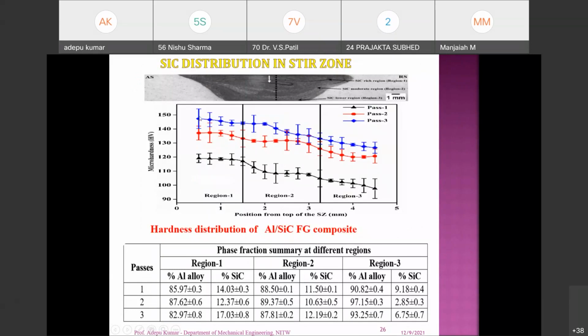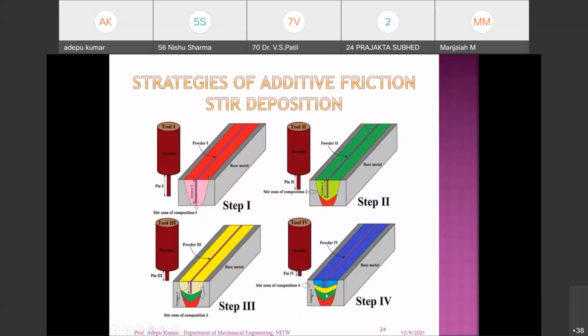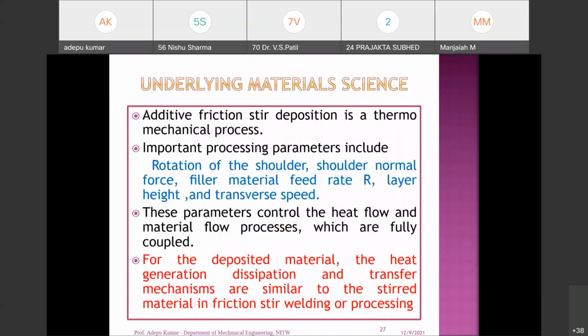Let us say the initial hardness is 120 to 150 HV, and 30 HV is improved by doing this process. So this part becomes a functionally graded material product. You can also extend it to other regions with the same principle, so the entire block becomes a functionally graded material. Like this, you can get functionally graded materials by depositing the reinforcement with different compositions, so that you get variation of the properties in terms of directions.